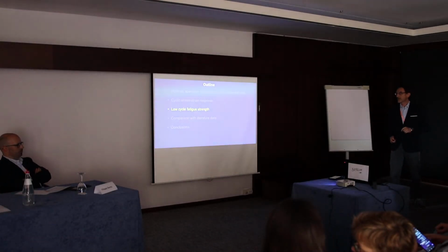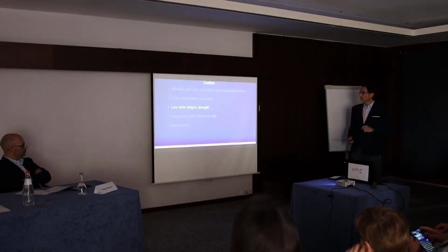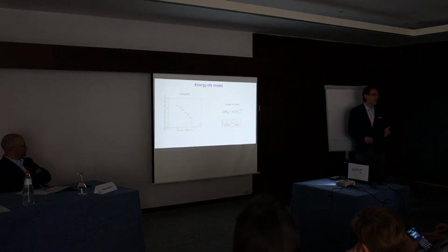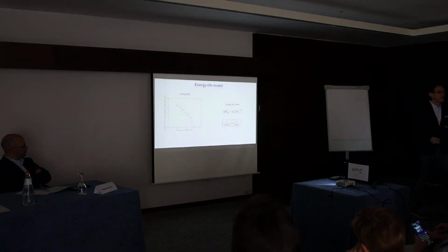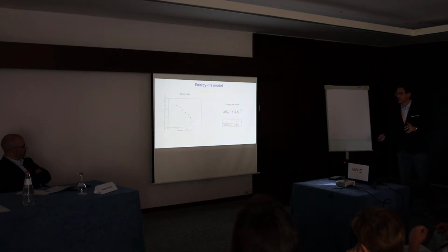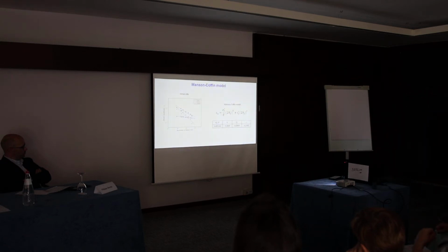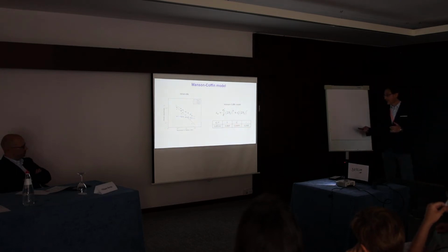So now, concerning the low cycle fatigue strength, first of all, as I told you, we tried a correlation between this energy parameter and the number of reversals to failure. This is the fitted line in log-log scale. Well, the fitting would be considered pretty good, although there are some points that deviate from the average line. And in addition to this energy-life model, we considered and fitted the more common Manson-Coffin model. And again, the fitting seems pretty good, apart from one point.